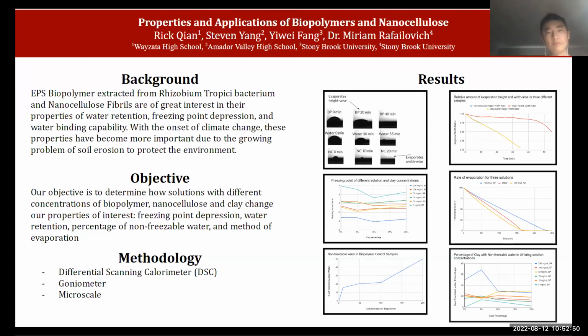All right, moving to the middle, we have the freezing point versus clay percentage found through DSC analysis. We found that the amount of freezing point depression increases with increasing concentrations of biopolymer, which follows the principles of freezing point depression. Nanocellulose has a lower freezing point at equal concentrations compared to biopolymers. Our microscale evaporation analysis shows that biopolymers have a lower evaporation rate than nanocellulose and water, having better water retention rates.